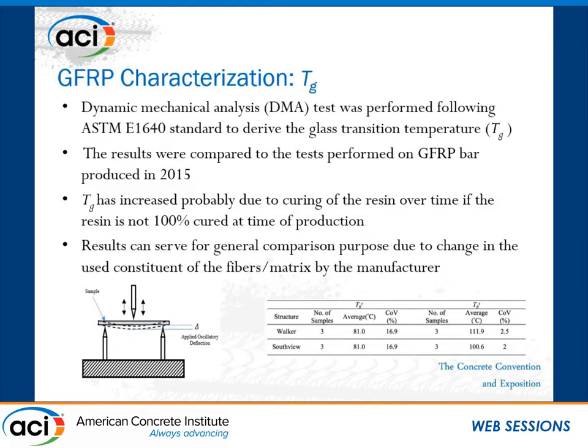That parameter is also really critical for us, because this is the temperature beyond which GFRP bars lose their ability to transfer the load dramatically, because the state of the resin changes from solid to a liquid type of state. So the dynamic mechanical analysis was performed following the ASTM E1640. And again, the result, the same as the shear test, was compared to the samples produced from the same manufacturer but produced in 2015. And again, what we found was approximately 25% of increase in the glass transition temperature during the years.